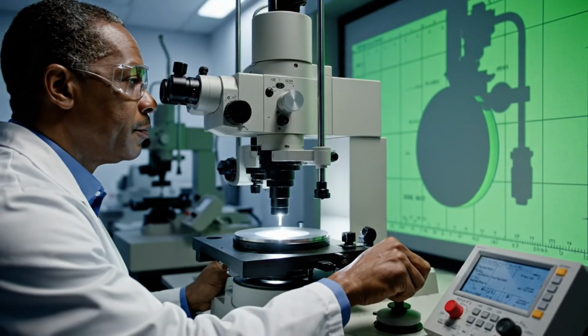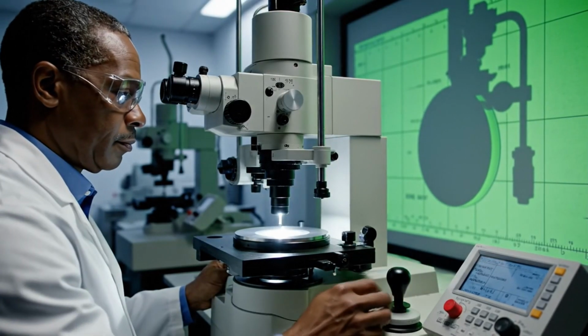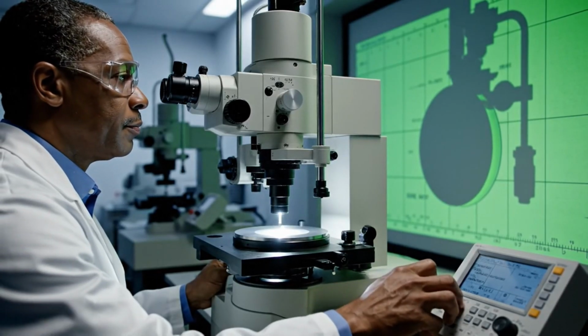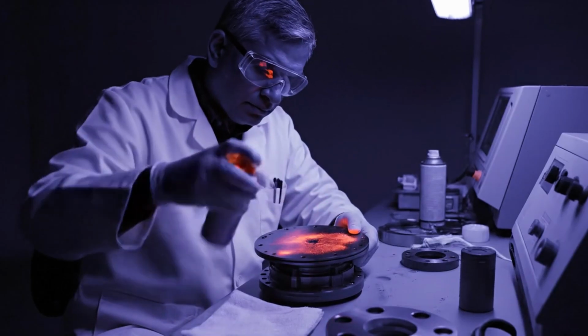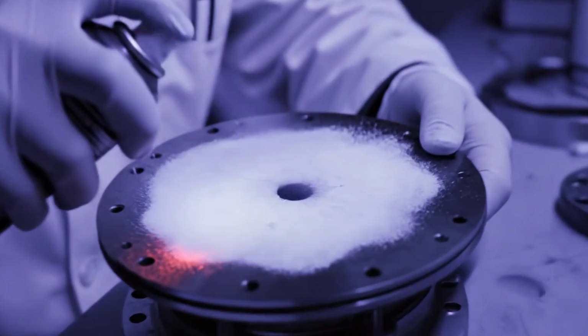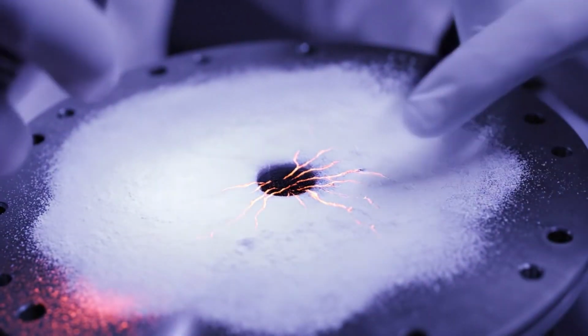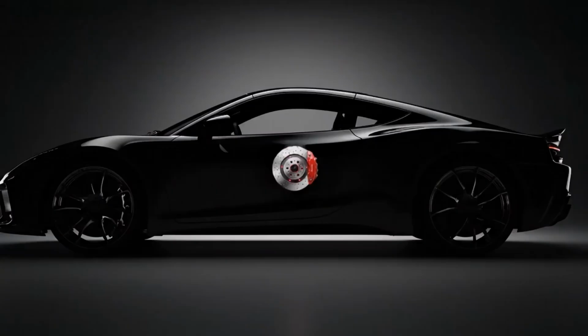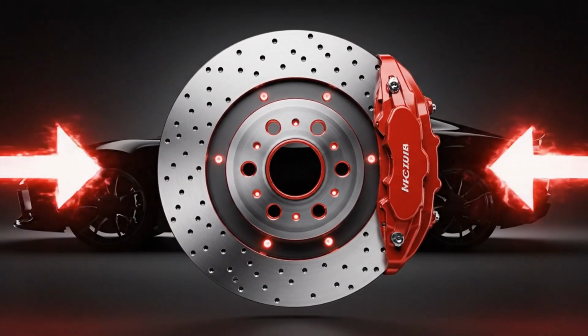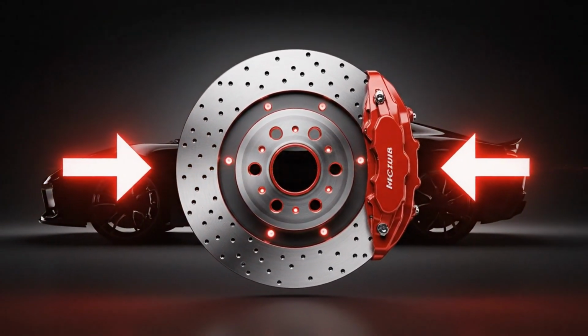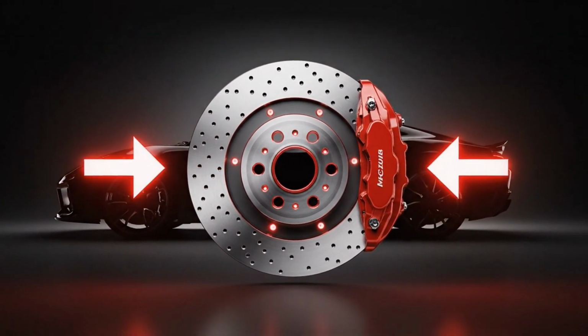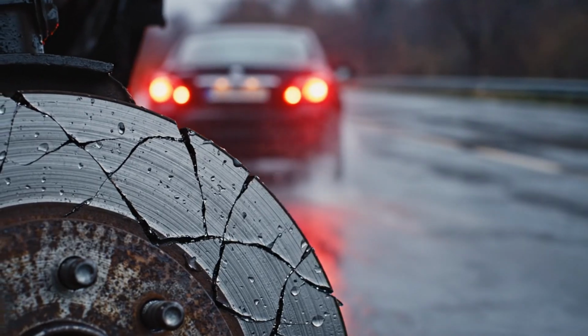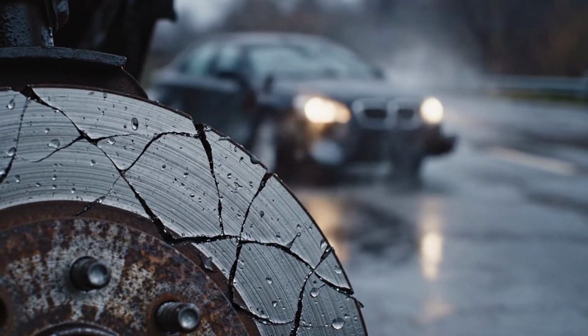In addition to geometry, the integrity of the material is also evaluated. Depending on the manufacturer and the level of requirements, some parts may undergo non-destructive testing to look for internal cracks, porosity, or discontinuities. The reason is clear. A brake disc operates in one of the vehicle's most sensitive systems. If it fails, it's not just a part that's lost. The very ability to stop the car is compromised.